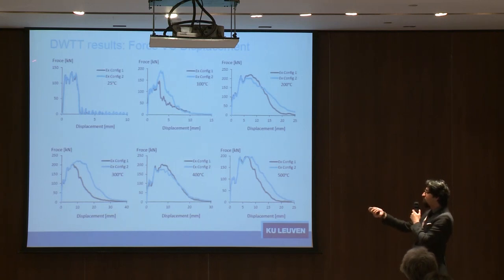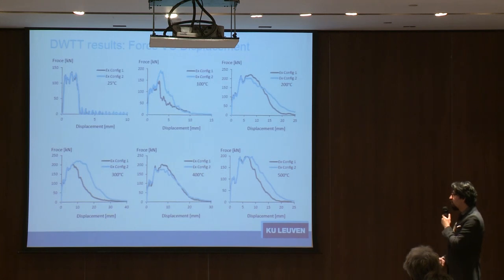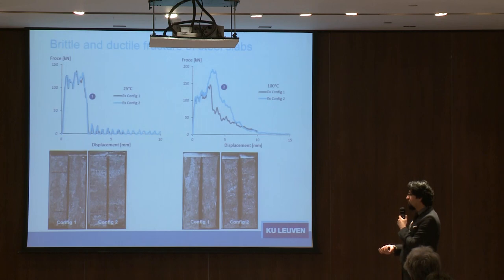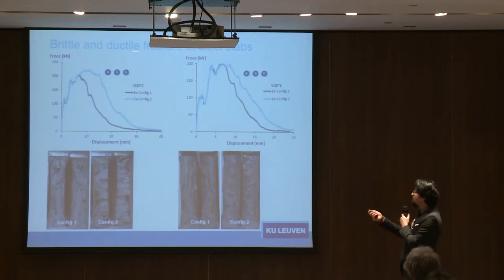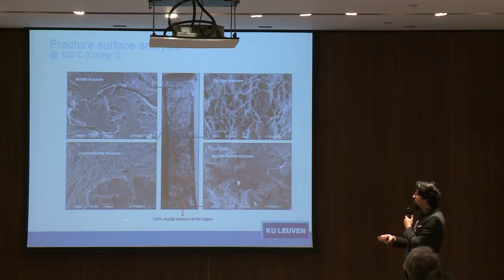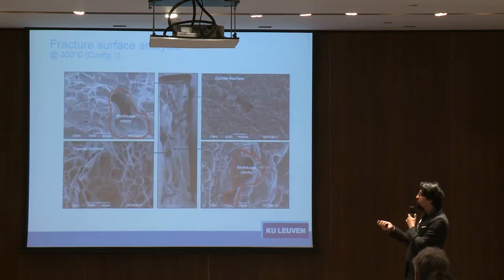Looking at force versus displacement curves, at room temperature behavior is quite brittle, at higher temperatures there are deviations between the two configurations, and at the highest temperatures behavior is mostly ductile. Examining the macro fracture surface, at room temperature the material is quite brittle; at 100°C we see a combination of brittle and ductile fracture. At high temperatures — 300 and 500°C — we have quite ductile behavior with shrinkage and fully ductile crack propagation for both configurations.